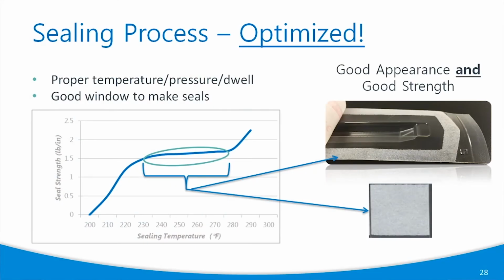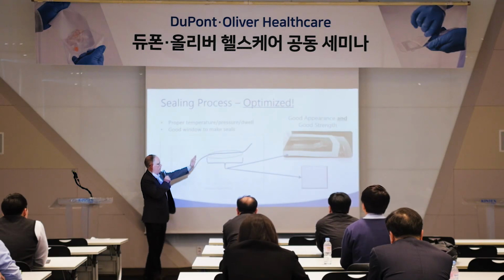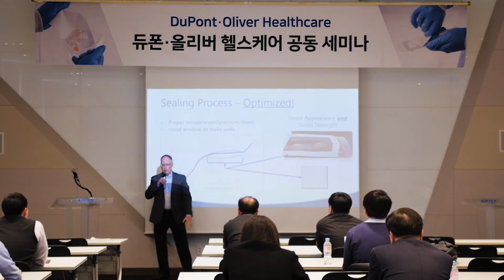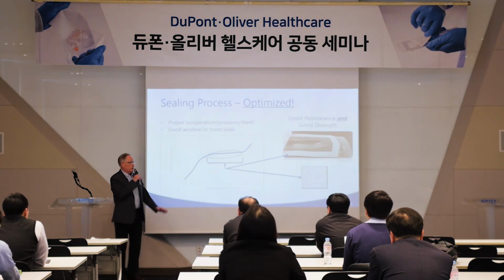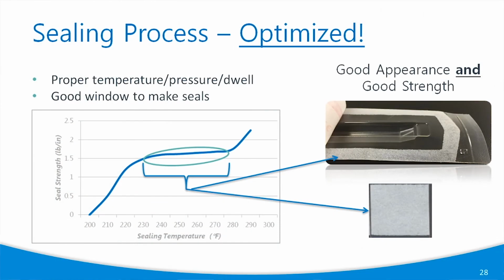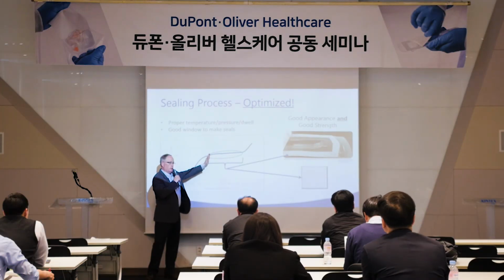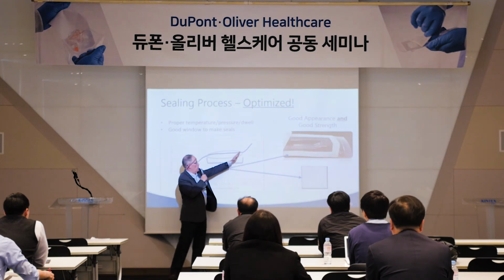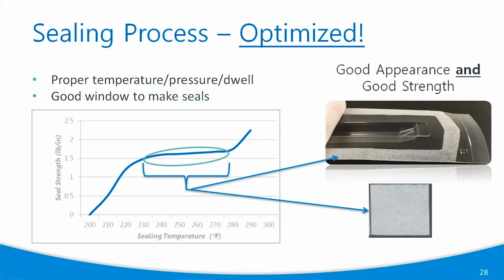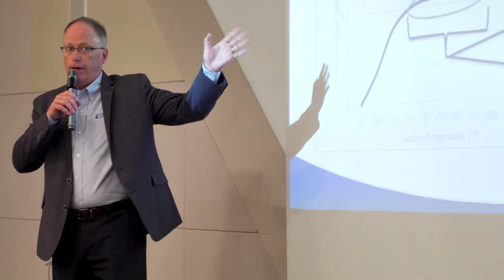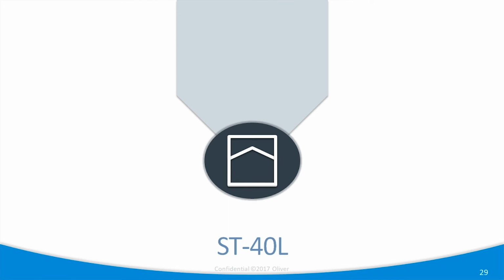And this is where you really want to be at the end of the day. Once you've gone through your experimentation and your validation, you want a window to work within. And we talk a lot about ISO 11607 in our industry, but ISO 11607 tells you should have a window to work within in your sealing process where you've got low temperature, low pressure, low dwell time, and also a defined window at the upper limits where you've got a consistent output of peel strength, you've got a good cosmetic looking seal, and that is where you want to have your validation defined at. So we're going to transition to a new grade of Tyvek, and it's going to be covered by the DuPont folks, but you can go to the next slide.